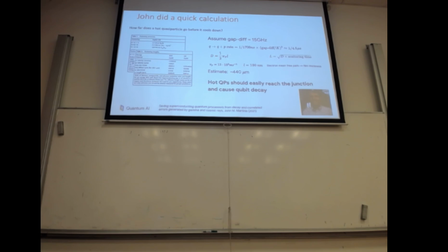Let's assume that the mean free path of the aluminium is the thickness of this aluminium, which is 100 nanometer. So basically L is 100 nanometer. Let's take the Fermi velocity of this aluminium. What you get is an estimate of the typical distance. Basically, what you find out is that the quasi-particle, before going down in energy, travels for 440 micrometer. So it is right that there should be some hot quasi-particle that could easily reach the junction and cause a qubit decay.